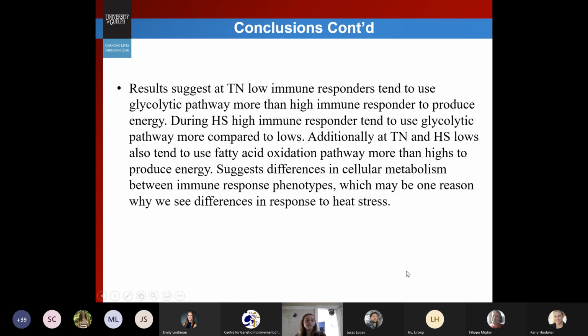Additionally, our results suggest that at thermoneutral, low immune responders tend to use the glycolytic pathway more than the high immune responders to produce energy, whereas during heat stress, the high immune responders tend to use the glycolytic pathway more compared to lows. Additionally, we saw that at thermoneutral and heat stress, lows also tend to use the fatty acid oxidation pathway more than the highs to produce energy, which suggests differences in cellular metabolism between our immune response phenotypes, and may be one reason why we see differences in response to heat stress.